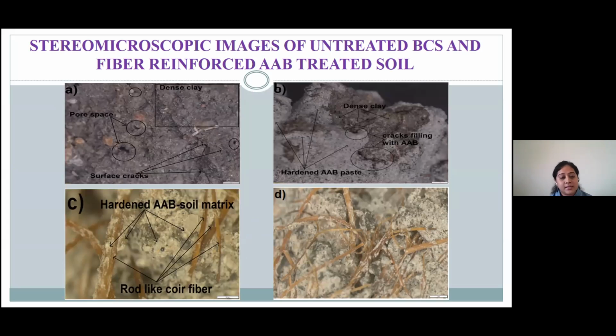These surface characteristics are studied using a stereo Olympus microscope setup. The surface images reveal a light reddish yellow color, indicating the presence of iron and the illite and smectite groups. You can see the pore spaces and surface cracks are visible. A thin layer of hardened AAB paste can also be observed around the clay particles and the fibers.